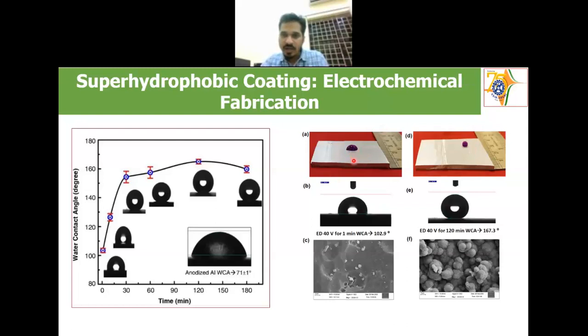This is the uncoated sample. This is the 1 minute deposition, and its water contact angle is 102 only. That means it's hydrophobic but not superhydrophobic. There is no rolling off. But as we increase the deposition time, the contact angle increases. You can see 120 minutes.